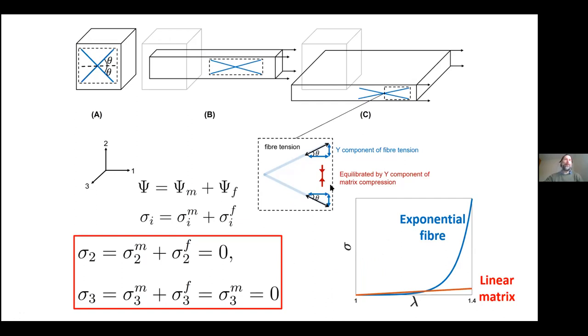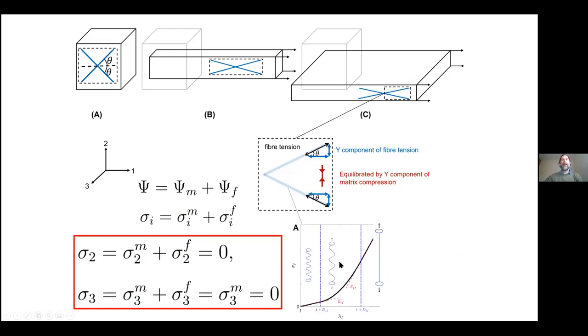So what's happening here? Well, basically, the fiber develops an extremely high stress because of this nonlinearity. So that means that in this plane, in the Y direction, the matrix must perform a very large compression so that we can satisfy this equilibrium equation. So that means if the fiber is developing a very large tensile component in the Y direction, to satisfy this stress-free boundary condition, the matrix must develop a very large negative compression. So the matrix becomes very compacted in this Y direction.